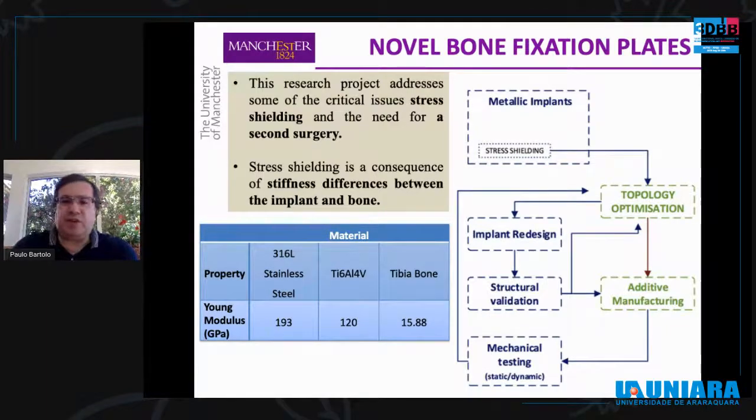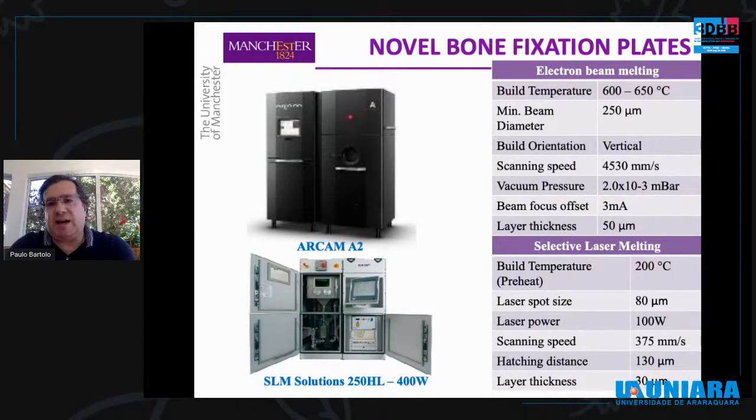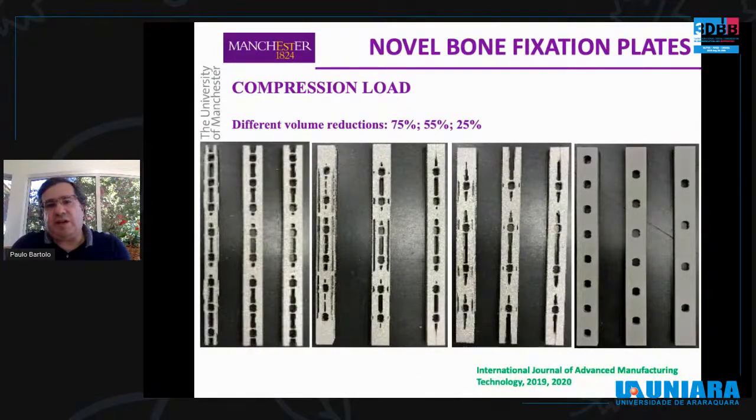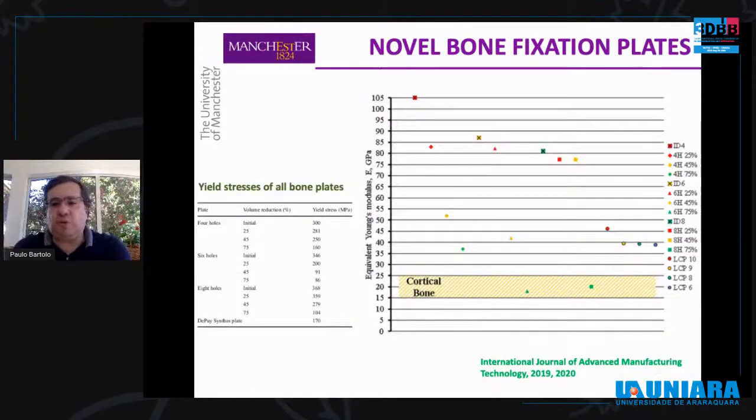We ran topology optimization considering different loads and volume reductions. And as I mentioned, we use two different powder bed fusion technologies, but using different principles to print the plates. One was electron beam melting and the other one was selective laser melting. The plates were optimized considering different loading conditions and different volume reductions. And by the end, it was possible to obtain a couple of new designs with properties in the cortical bone region. So we were very happy